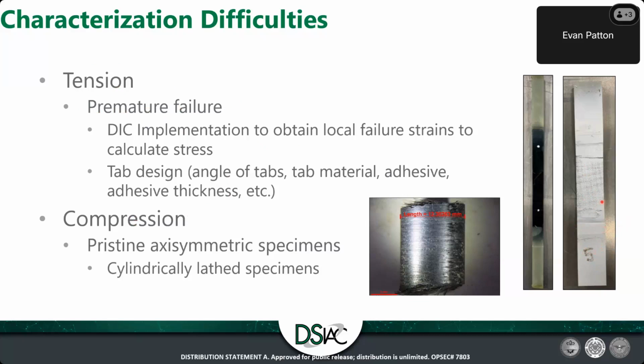And then there's also an issue with off-axis fibers. So I kind of refer to it as almost like piano string, because when you pull these specimens in tension, you can kind of hear plucking from each individual fiber rupturing. And that's simply due to some of the fibers being under a higher load just because of the way it was manufactured. And if you think about it from a metal standpoint, you're pulling the entire material at the same time. So it's a very representative sample of what you're seeing. But with the composite, you're pulling on all these fibers. And if some of them are carrying more load than others, it's not necessarily indicative of the load that it's actually carrying or can carry.